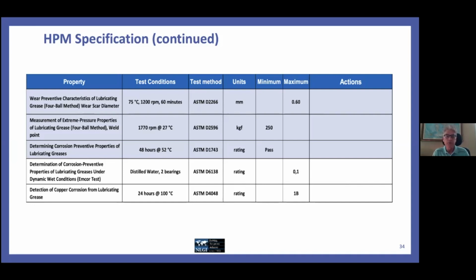However, we felt that that was not necessarily the most challenging corrosion test, so we added the Emcor test, the dynamic ASTM D6138 test with distilled water. It's distilled water; we'll get to salt water later on. But this test adds a completely different perspective to corrosion compared to the static D1743 test. And again, we came very quickly to agreement that 0 or 1 for the 2 bearings was an acceptable maximum for that test.